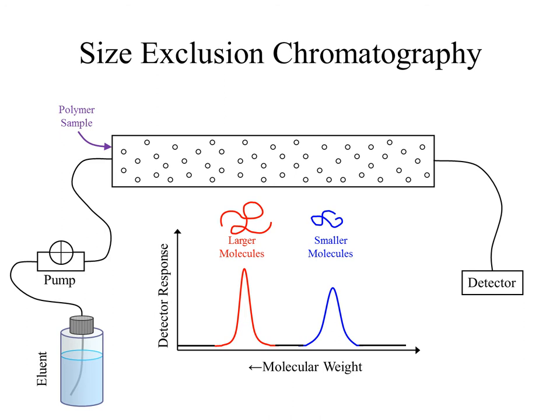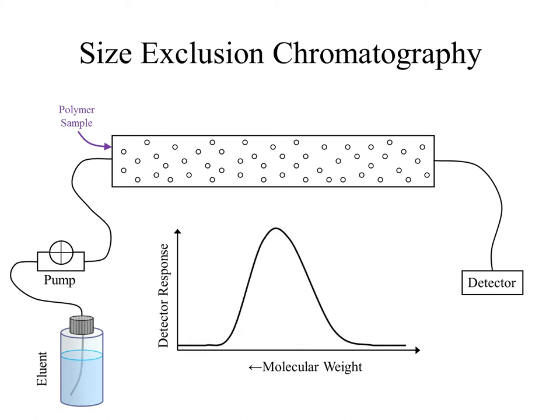On the other side of the column, we'll need a detector capable of noticing when a polymer molecule passes by. This is typically a refractive index detector, or RI detector for short. Now, our detector just stays on the whole time, waiting for something to pass by. We will plot the detector response versus the volume of eluent that has been pumped through here. Knowing the pump speed allows this x-axis to be converted into time, referred to as either elution time or retention time. As we start pumping eluent through, we see the polymer sample begin to move through the column. Since the larger red molecules have a smaller volume available to them, they start winning their race through the column. The smaller blue molecules take their time getting through the packed particles, but eventually do come out. The detector did its job and picked up concentrations of both molecules, plotted here. Now, if these were standards, we can calibrate our system so that the volume of eluent, or retention time, can be converted to molecular weights.